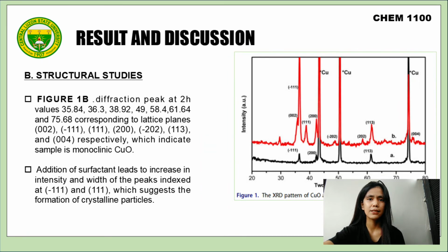Next slide please. The figure shows diffraction peaks at 2θ values 35.84, 36.3, 38.92, 49, 58.4, 61.64, and 75.68, corresponding to lattice planes 002, -111, 111, 200, -202, 113, and 004 respectively, which indicates sample is monoclinic copper oxide. Addition of surfactant leads to an increase in intensity and width of the peaks indexed at -111 and 111, which suggests the formation of crystalline particles.